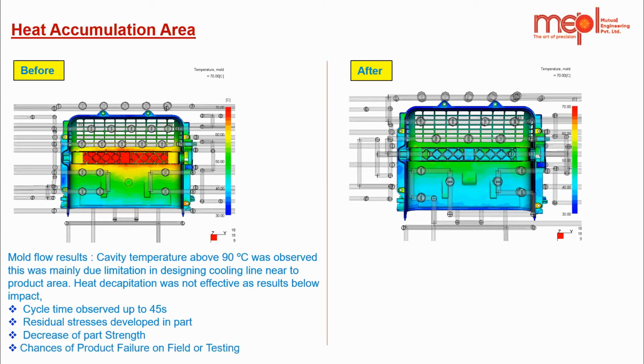It was nearby 45 seconds, due to which residual stresses were also developed in the part, and we could not achieve the part strength and dimensional stability. So there could be chances of product failure in the field or in testing.